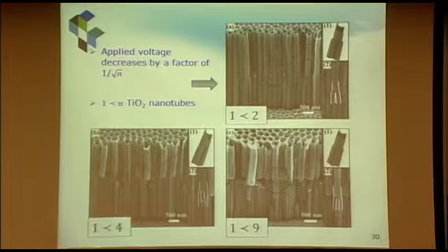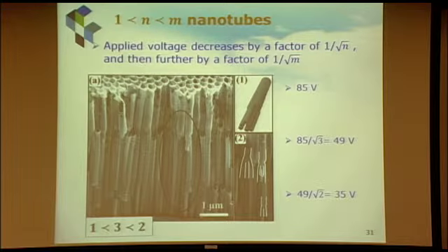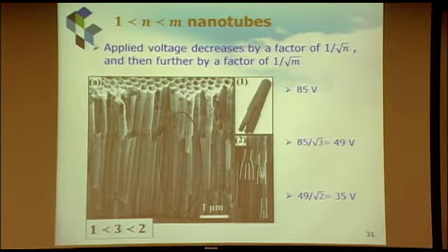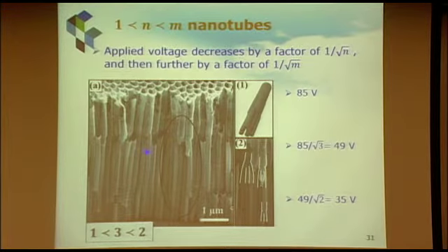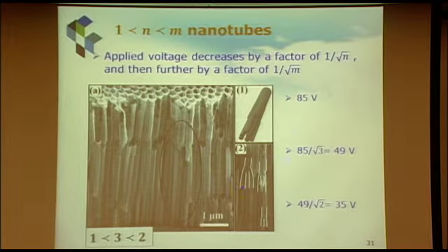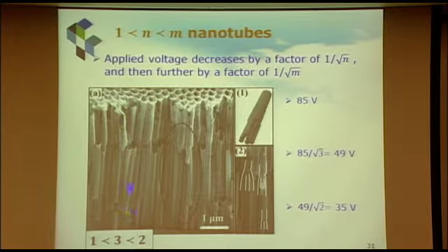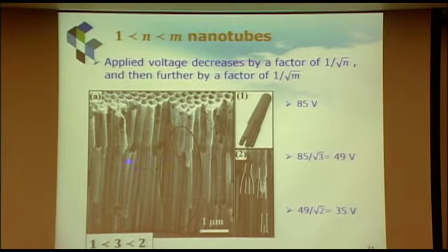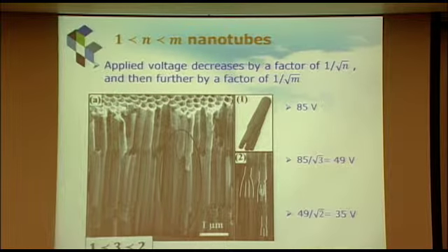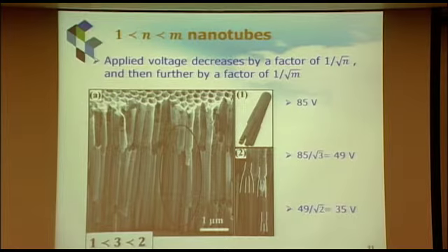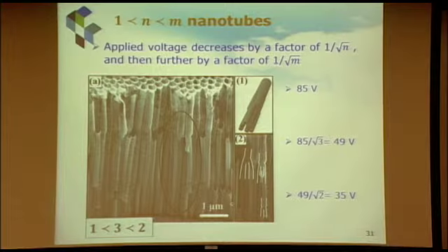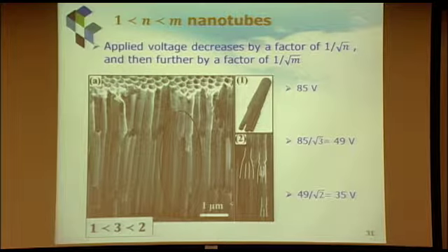You can do that. And another possibility is we can not just get 2 layers of tubes or pores with these different sizes. We can do it continuously. In the middle, we change this in 3 steps. And then we get pores like split 1 into 3, and then split each one of these into 2 more, and so on. So we call these branched pores, and the main rule to follow is the relationship between the voltage and the surface area.